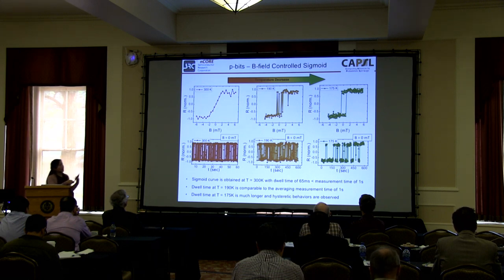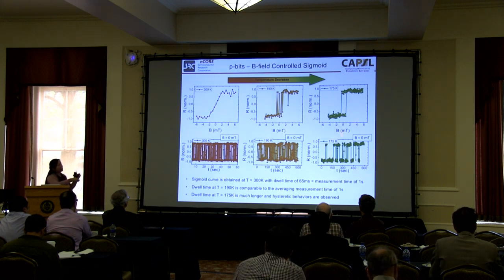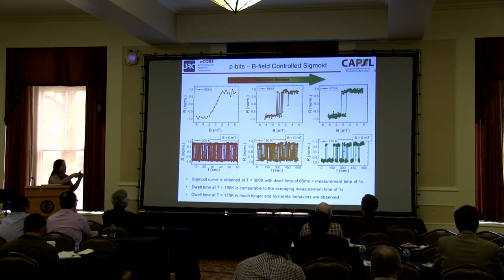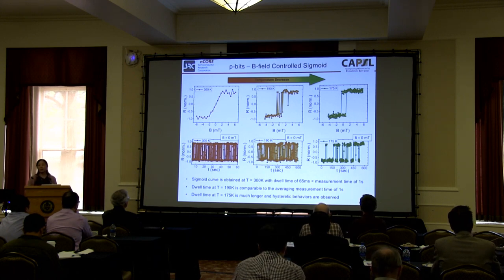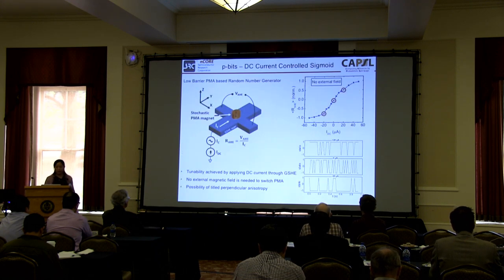And the temperature study is similar to what I mentioned before. It's just to prove that this sigmoid curve indeed comes from the random telegraph noise. Because when I go down in temperature, when the retention time of the magnet is long, then you do not have the sigmoid curve anymore. So on the same magnet, decreasing the temperature and seeing the hysteresis curve being recovered was the proof that we do have a system that is randomly fluctuating.